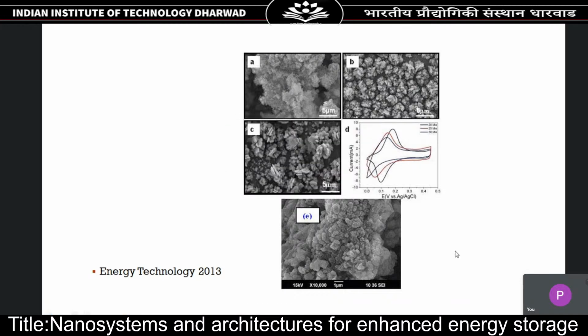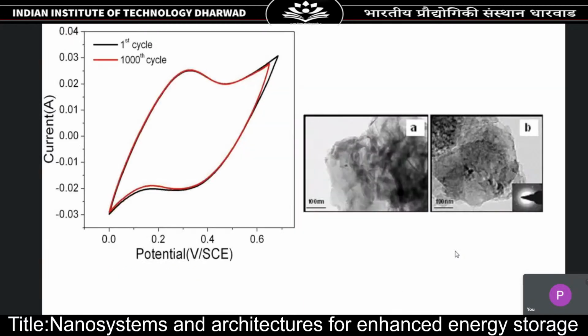And this was published in Energy Technology in 2013. So this shows the cyclic behavior under cyclic voltammetry. You can see that even after 1000 cycles, it has very good fidelity. And we also carried out TEM of the composite structure as well as SAED. So you can see that it has a very flaky and layered structure.